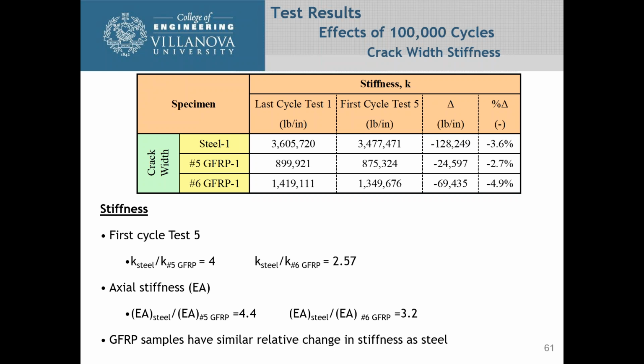If you look at the change in slope, it was minus 3.6% for the steel, 2.7 for the number 5 bar, and 4.9 for the number 6 bar. So you had a change in deflection, a change in stiffness, but the slope didn't change too much, so it wasn't that bad. So also the thing that this is telling us is that the GFRP bars' change in stiffness is relatively the same as the change in stiffness that we got in steel.